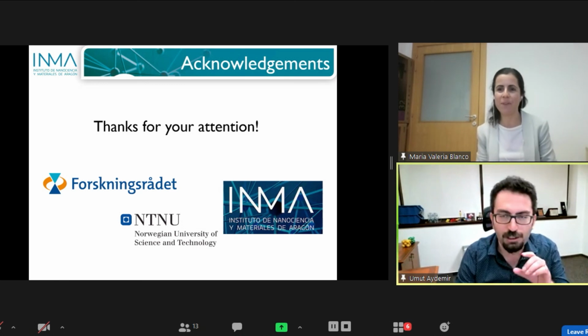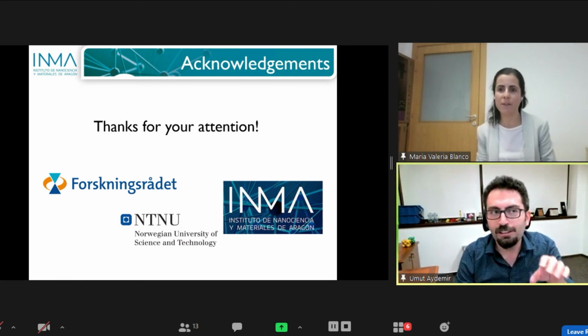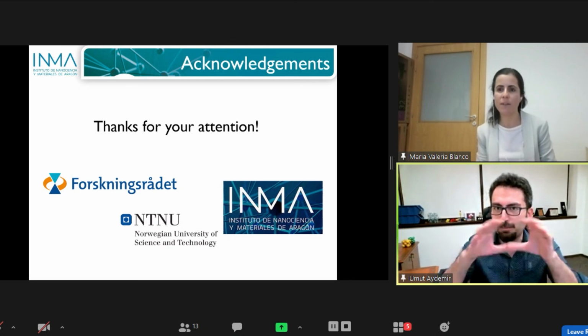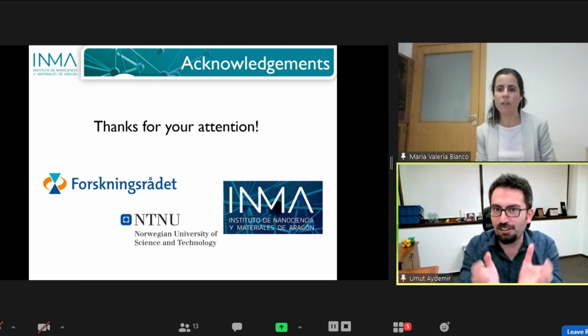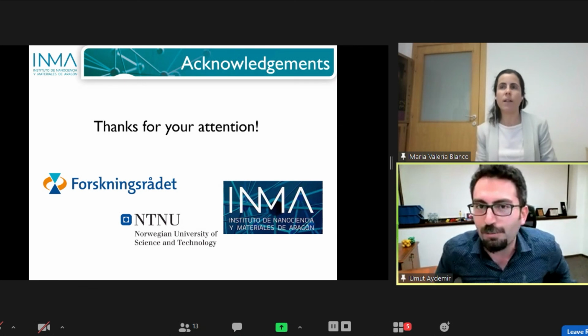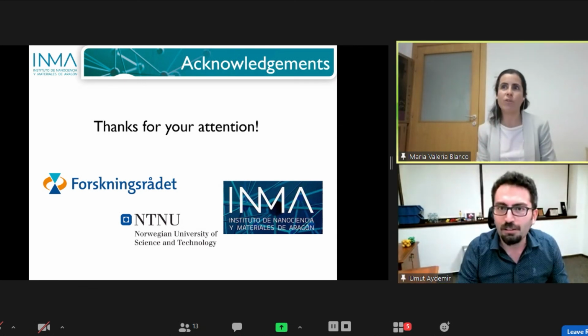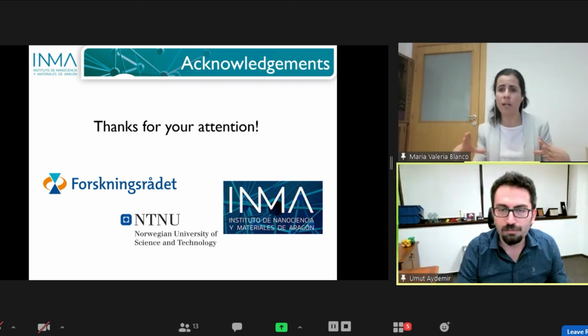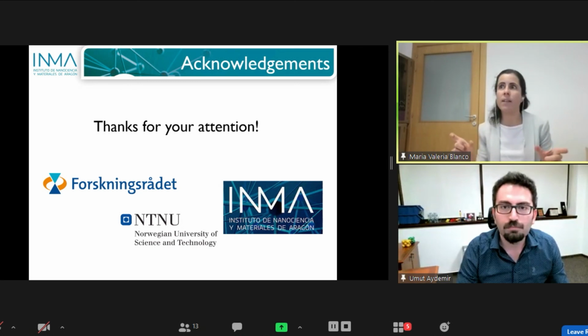Ms. Blanco, I have one quick question. What happens if, instead of coating silicon dioxide, you coat the silicon? Could it be a little more stable because it would be encapsulated with the carbon shell? Then it would maybe reduce the cracking. That's one of the strategies to improve silicon: first to make some nanostructure, and also to have this carbon layer that will buffer a bit. But the difference in volume is more than 300%, so you cannot solve it just with this.